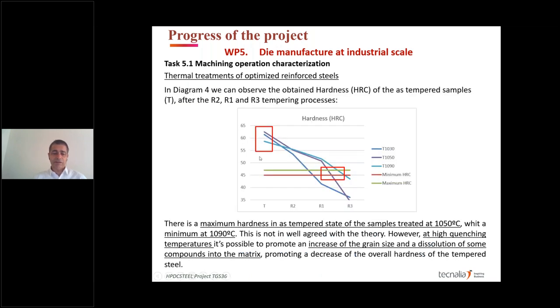And the main first results were surprising: the higher hardness we don't get with the maximum temperature, which was 1090 degrees, but we get it with 1050 degrees. We think that it could be related to a different grain size or some dissolution of carbides into the matrix. We also see here a kind of area around 45 Rockwell C hardness, which was the area where we wanted to work.